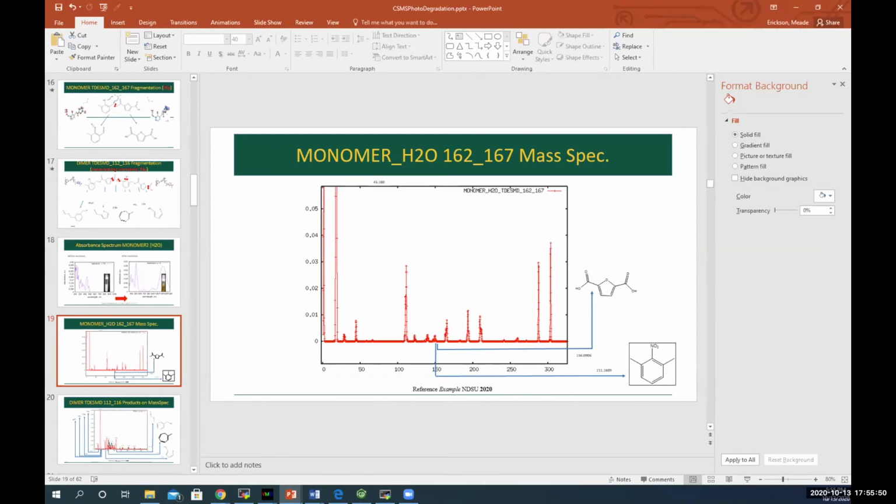Oh, okay. Show how the reaction goes as we expose the polymer to light for longer and longer time. Yeah. Like if one makes it too short, then there will be only a single peak corresponding to the whole polymer, the rightmost peak on your diagram. And as time goes by, it will develop these main fragments which are about 2 times lighter than the original, and then smaller molecules close to zero will pop up. Yep. Okay. Yeah, we can discuss that.